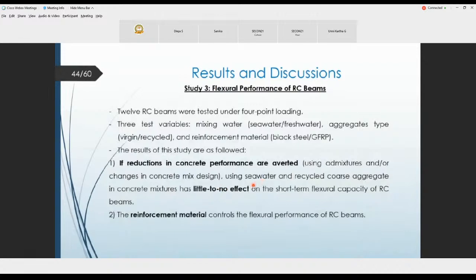Study number 3: we studied the combination of seawater and recycled aggregate in actual reinforced concrete beams, combined with FRP bars. We constructed 12 reinforced concrete beams tested under 4-point loading. Three test variables were used: the mixing water, either seawater or freshwater; aggregate type, either natural or recycled; and the reinforcement material, either regular black steel or GFRP bars.